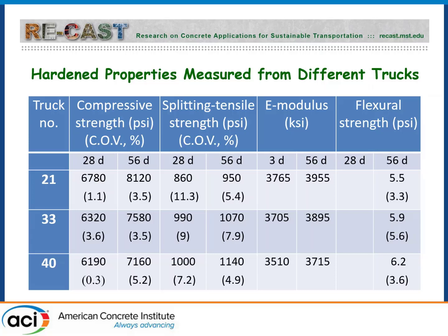Compressive strengths at different ages. In parentheses, you have the coefficient of variation. And when you sample something on the job site, anytime you're less than 5%, it's really excellent. So that means the concrete cylinders were properly sampled and prepared and transported and cured. This is all moist curing after getting them to the lab.